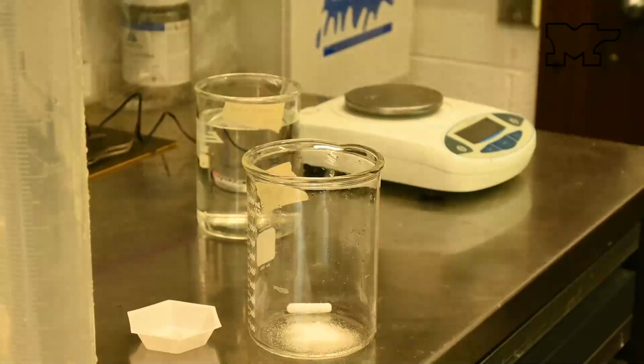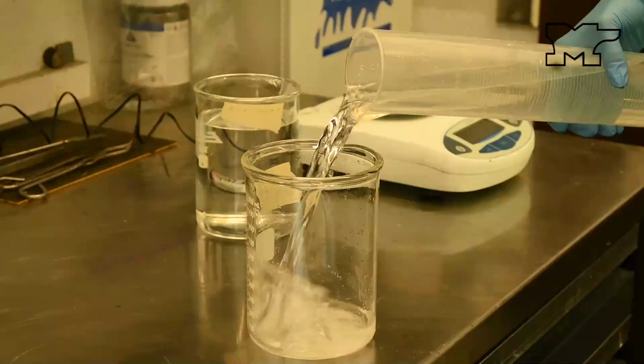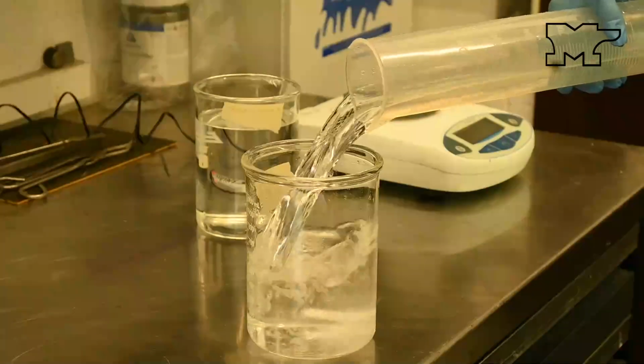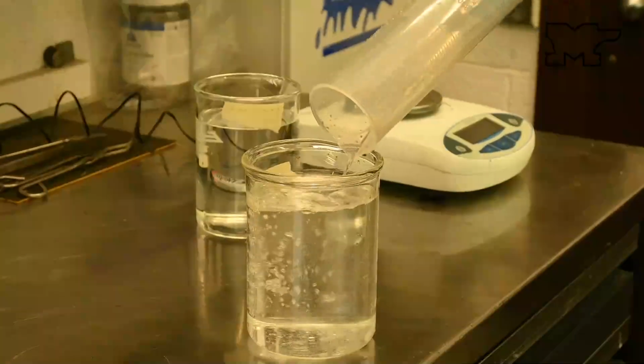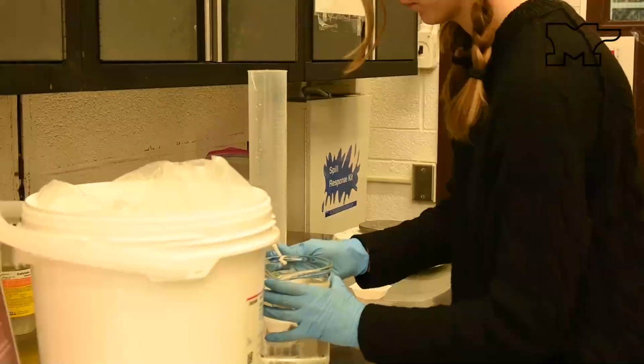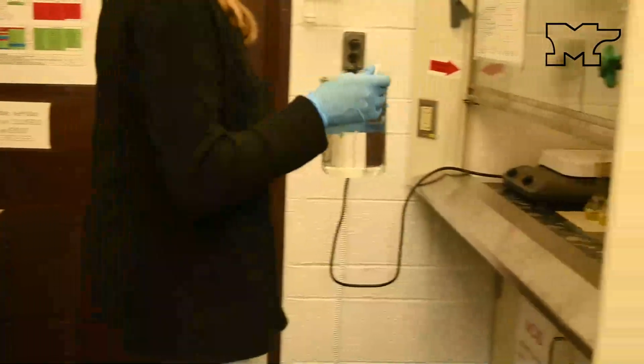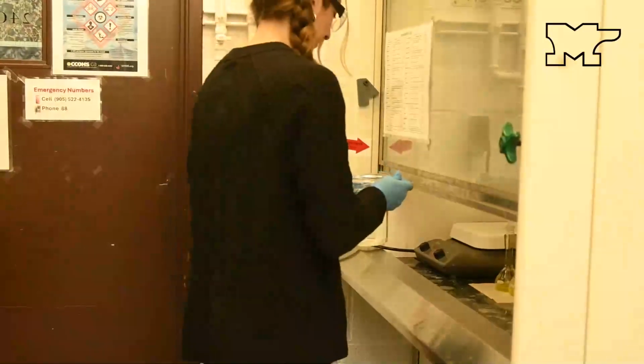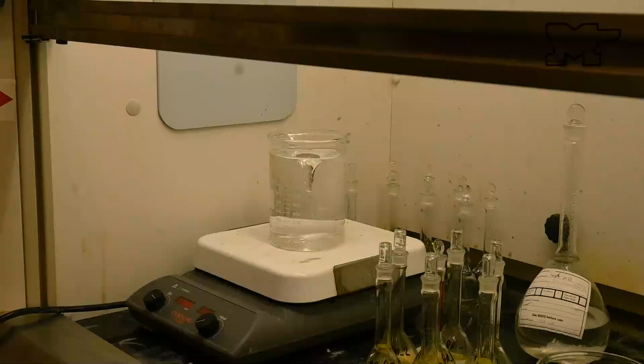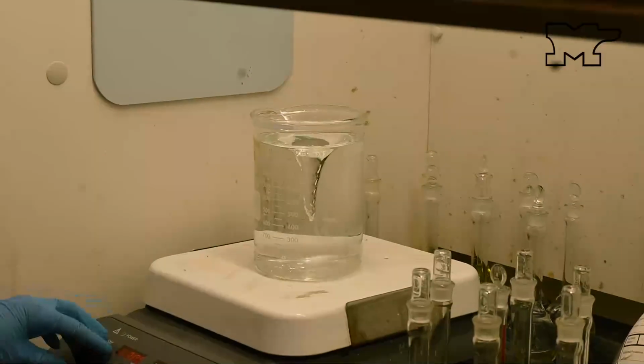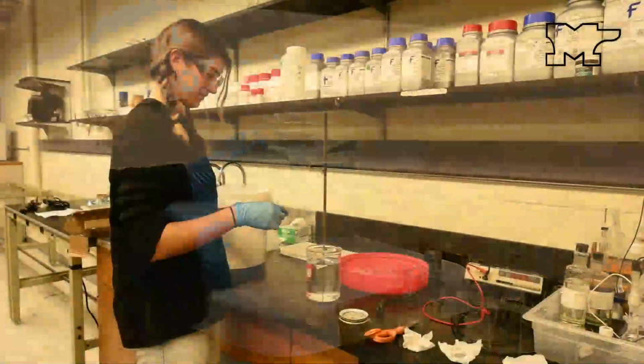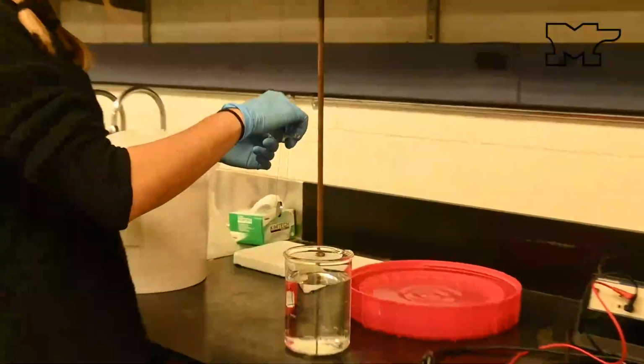The last tests which we performed were corrosion. As our blade could potentially face harsh coastal environments, we decided to perform a long-term saltwater immersion test. Both as-received and heat-treated samples were placed in a 3.5% aqueous sodium chloride solution for 430 hours, and then weighed to measure mass loss and compare to literature values.